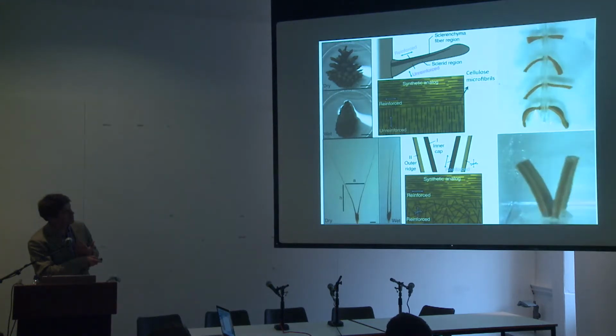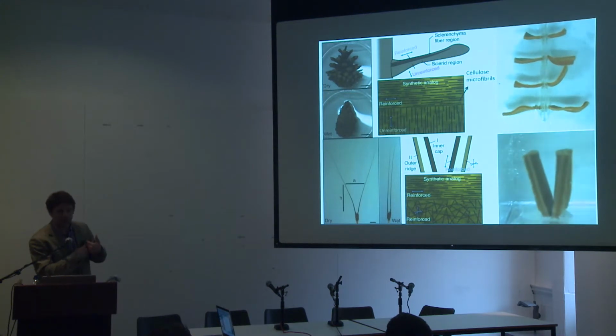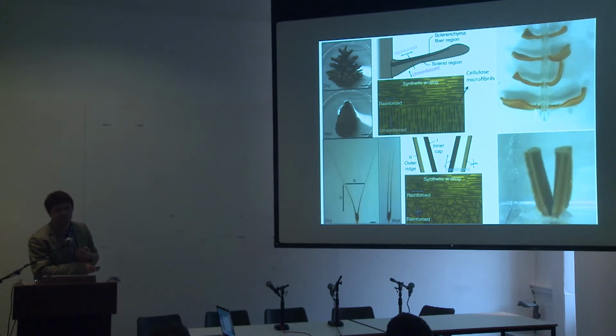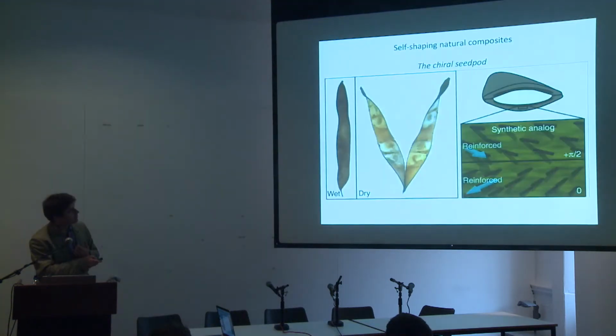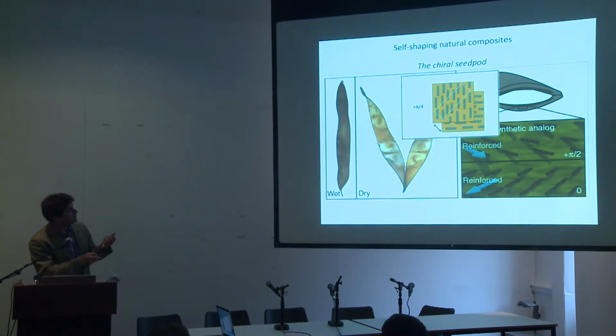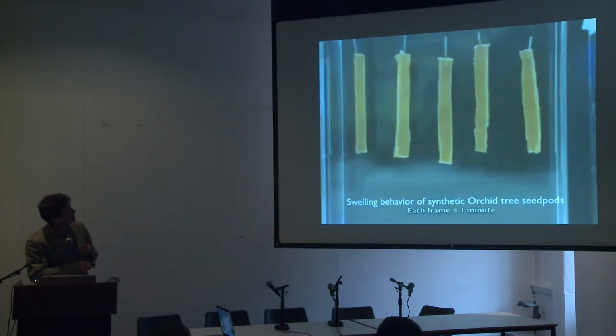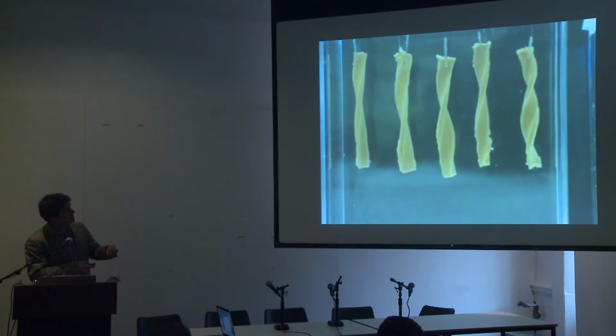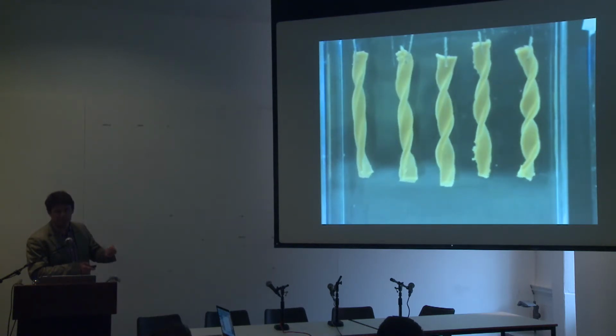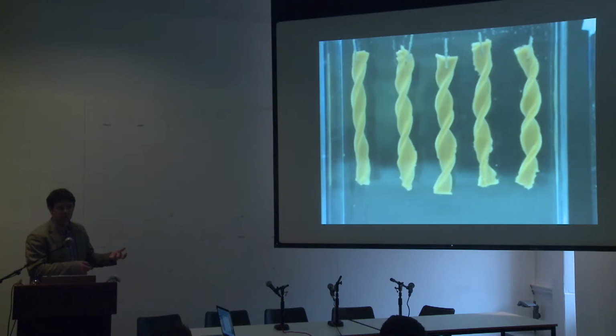If you do that and put it in water, you see that it nicely replicates this bending effect. However, this is rather easy to do with metallic bilayers. What is more interesting is actually this twisting effect. And here, for us, would be very easy to achieve because you can take the same bilayer but now cut at a 45-degree angle in order to reproduce this design. And if you put them in water, you see that they nicely reproduce the shape change that we program through the fiber architecture.